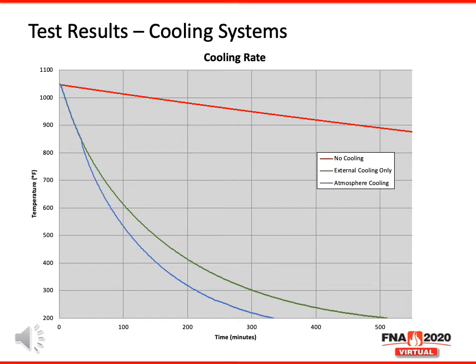So then if we look at using the external cooling system, this would be the green line on the graph. Again, this system is just the air cooling around the outside of the retort, significantly improved over no cooling whatsoever. And so that cooling rate to get down to about 200 degrees ran about 8.5 hours.